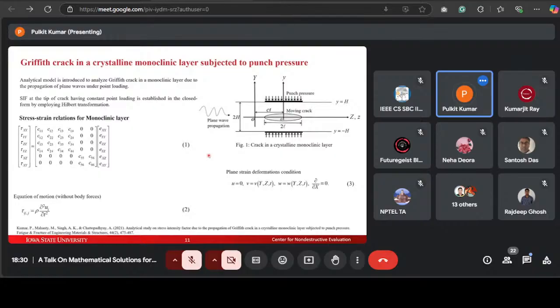Now let us consider an elastic plane problem of a moving Griffith crack of finite length 2L, influenced by the propagation of plane waves, placed in the mid-plane of a crystalline monoclinic layer of finite width 2H and of infinite extent. The considered layer is punched parallelly on the bonding surface on both sides at the corresponding location of the moving Griffith crack.